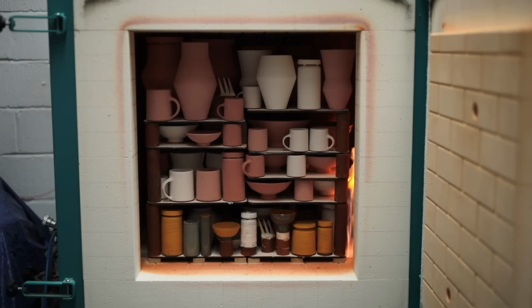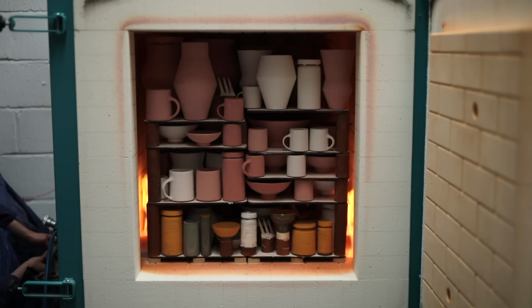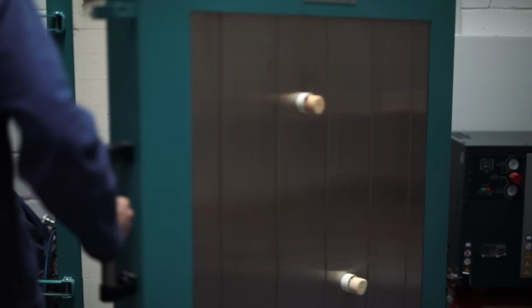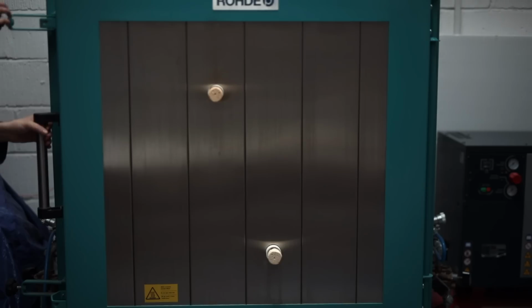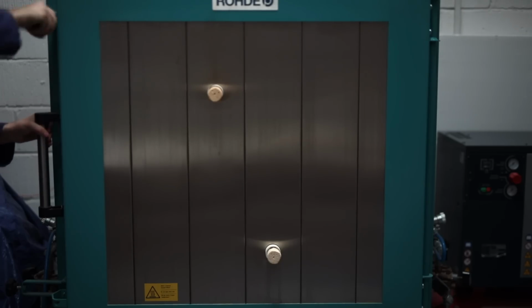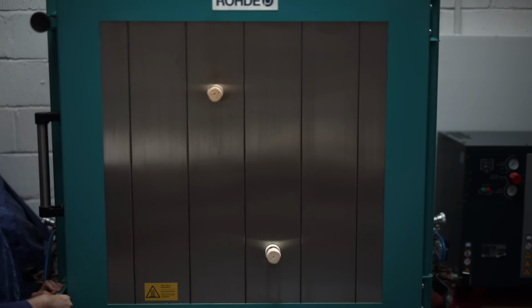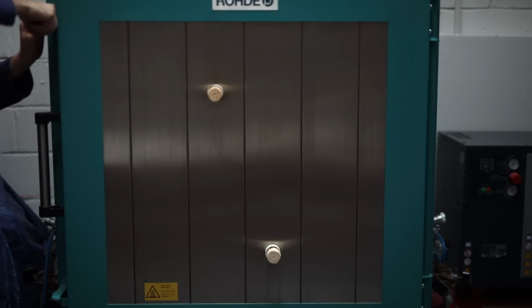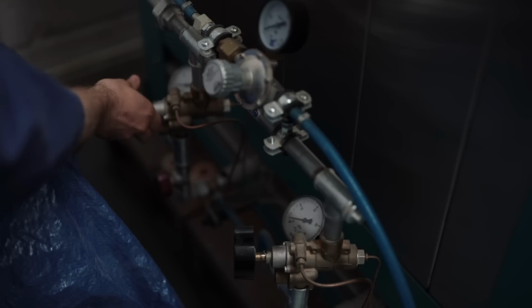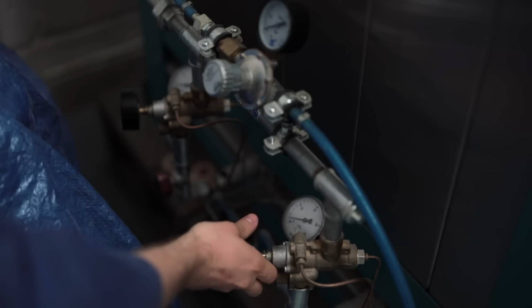And with the kiln packed, I can come in early the following morning to light and fire it. This process takes about 9 hours from beginning to end, and unlike my electric kiln which fires automatically, this kiln is controlled entirely by hand, by increasing or decreasing the gas pressure, controlling the air pressure, and altering the damper's position, which covers the flue of the kiln. The kiln is lit with the door open, which prevents any gas accumulating inside, which is suddenly ignited. The door is then tightly sealed, and the temperature is gradually increased, slowly at the start, as if you increase the temperature too rapidly, it might actually cause pots to explode.